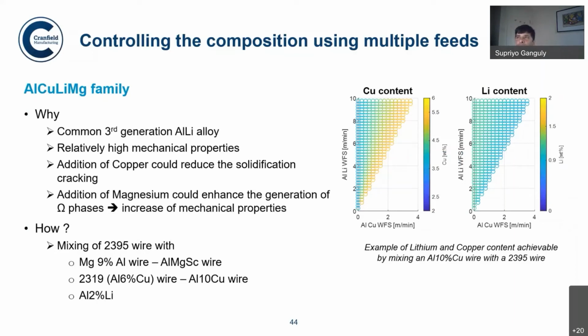Then we are also now trying to develop aluminium copper lithium magnesium alloys, which will reduce the solidification cracking sensitivity and give relatively high mechanical properties. Copper is added to reduce the solidification cracking tendency, and magnesium will generate omega phases, which are quite important to improve the mechanical properties. And it generally doesn't get overaged. With aluminum alloys, one of the major problems is overaging when you weld or do any kind of processing with thermal energy. This particular phase is quite strong, and it tends to overage quite less.